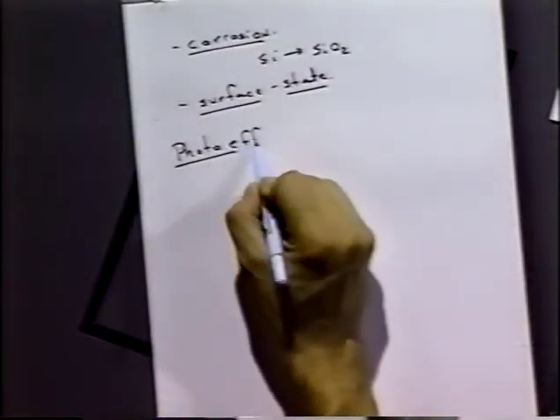And what can happen, especially if you have dangling bonds or broken bonds or hydrogen terminated bonds, is that those can be sites where charge can accumulate in a different way than in the bulk. And those different states then give rise to what they call, I forget the name now, states in the band gap. So otherwise forbidden states: remember we said there's no electrons going to be present in the band gap, now it can have electrons in there because of these surface species. And so that's not so great. So there's going to be a difference from theory and reality a lot of times due to those two effects. And we don't really have enough time to go through all the reasons and how to avoid some of those things.